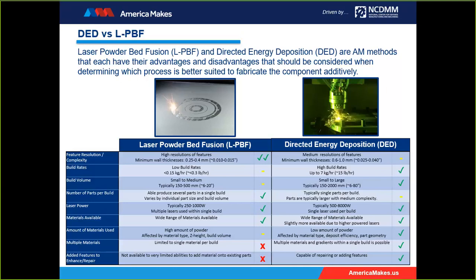The types of materials between the technologies are kind of a push, since the powder manufacturers can size the different particle size distributions out of a single heat or a single lot to meet the demand for the various technologies. However, the advantage for DED is certainly that it uses a significant amount of material less than laser powder bed fusion. The powder bed process requires a quantity to fill the XY surface of the build area, whereas DED is depositing material directly on top of the previous layer. So you could potentially use 90% less powder in a DED process versus a powder bed process. Lastly, DED is unique in its ability to add material onto existing parts, and we'll cover the enhanced features and the repair applications in the upcoming slides. But yes, you can certainly create parts with multiple materials in a single step.